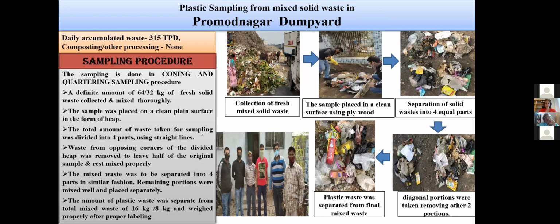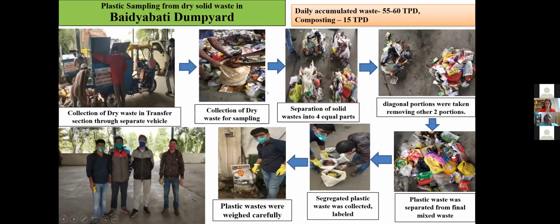We have visited 5 landfill sites, and we have generally applied the sampling procedure of coning and quartering in order to assess the amount of plastic waste in a fixed amount of solid waste, that is 64 kgs. This slide shows the dump yard in Pramod Nagar, in which we did some sampling. There is a daily accumulated waste of 315 tons per day in Pramod Nagar.